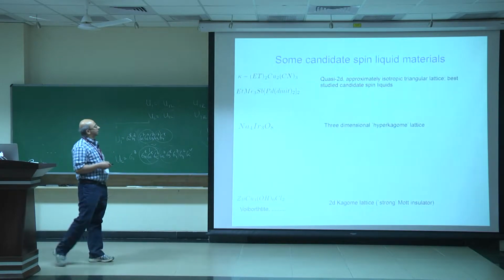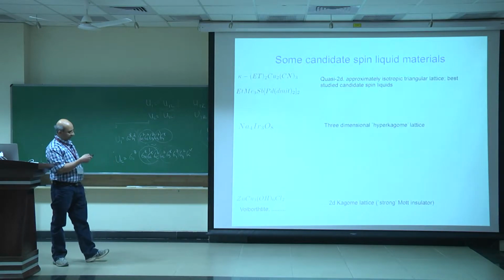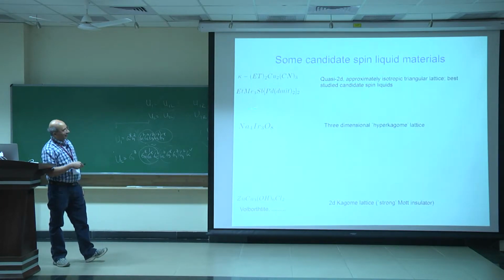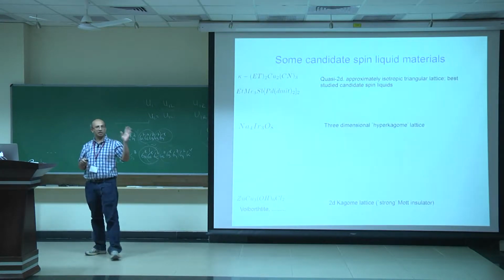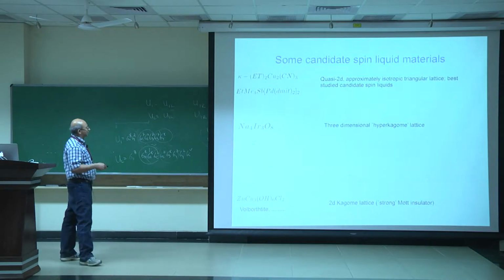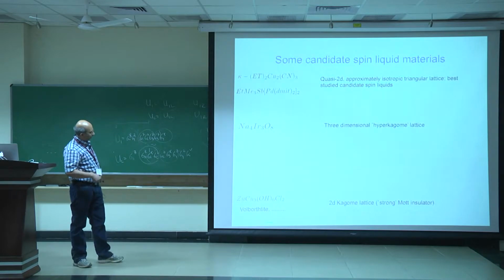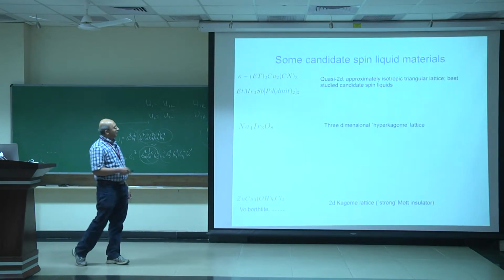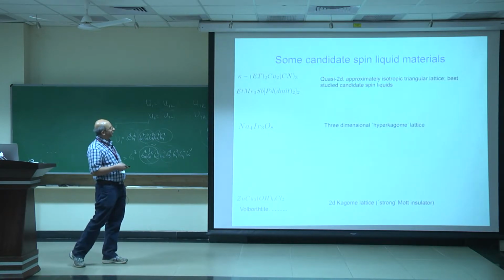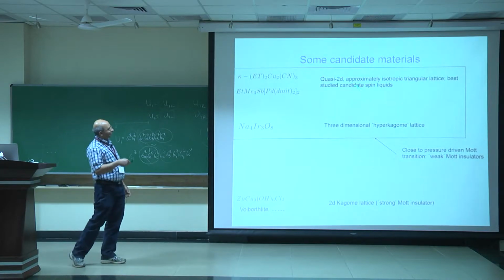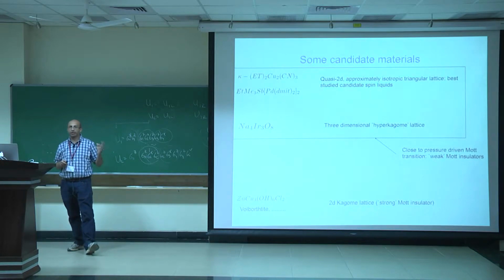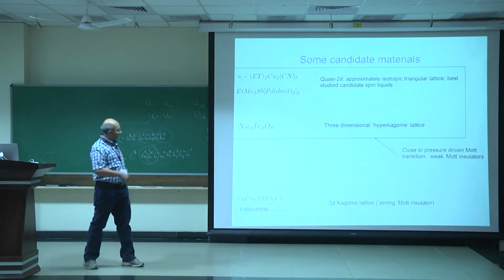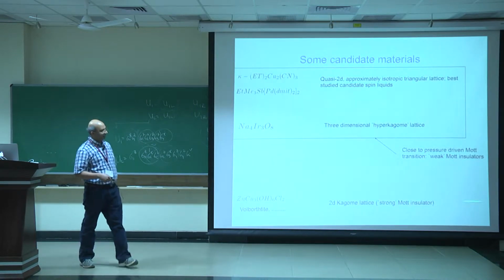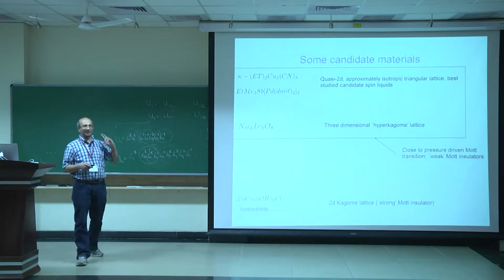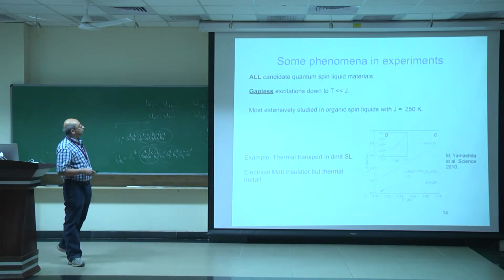So there are many candidate spin liquid materials, as I described in my first talk. There are these two organic spin liquids, which are in 2 dimensions. There's this 3-dimensional hyperkagome lattice system that Yogesh Singh, wherever he is, has been studying in his experiments and has been synthesizing. And there are also these 2D Kagome lattice systems, Herbertsmithite and Volborthite. Now there's a difference between these various spin liquids. The first set of examples all seem empirically to be close to pressure-driven Mott transitions. They're very close to the metal insulator transition, while these Kagome examples are what one may call strong Mott insulators. They're very, very far away from the metal insulator transition, and so clearly, theoretically, one has to think about these two classes differently. Okay?